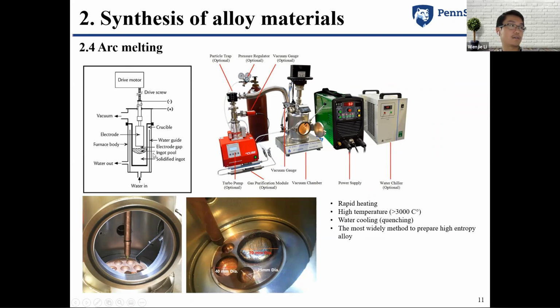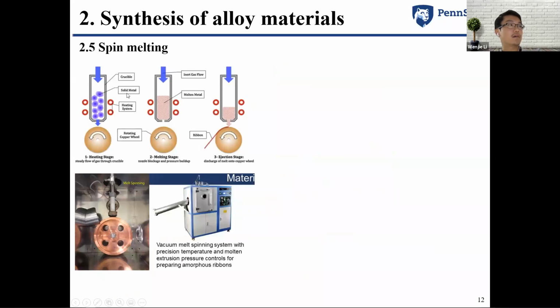This is how it looks like. The raw material is heated by the arc generated between the tungsten electrode and the raw materials located in the crucible inside the copper hearth. And the copper hearth can be cooled by circulating water. So right after the melting is finished, we just turn on the circulating water. This also provides a very fast cooling rate, in order to get the compositions that we desire that only exist at high temperature. And this arc melting method is also the most widely applied method to prepare high entropy alloys nowadays.